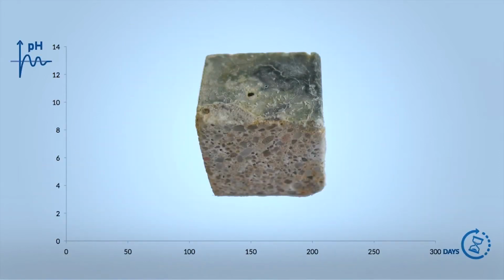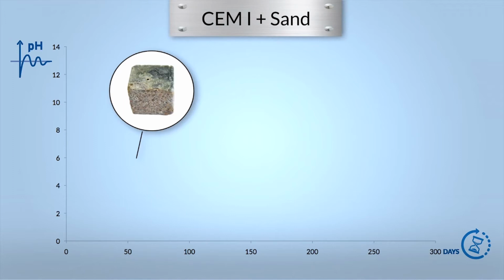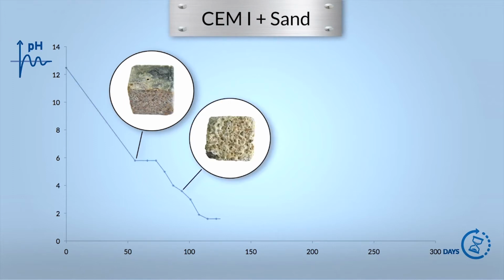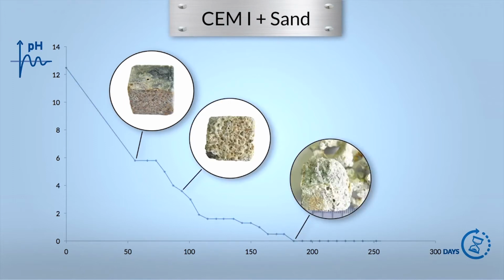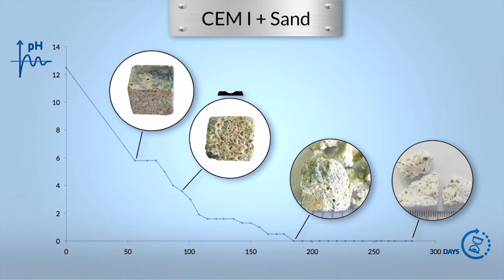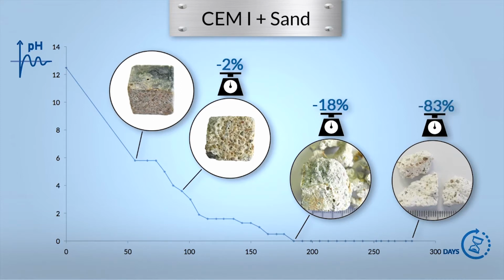These first results shown here are for the mortar cubes made with ordinary Portland cement, CEM1, and sand. Under the action of the bacteria transforming the H2S, the surface pH rapidly decreases below 1, dissolving gradually the cement matrix. Within a few months, the cubes are crumbling apart. The weight loss after 9 months is 83%.